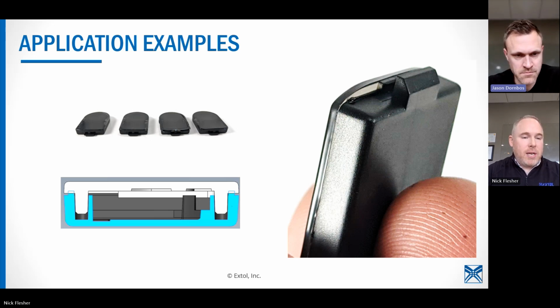These samples that you see up top, those 4 samples, actually were not a recommended weld surface area. We ended up collapsing on that. I think it was less than 0.1 millimeter. And then this was the recommendation we gave the customer, that CAD that you see at the bottom. You can kind of see that weld rib is inboard a little bit.